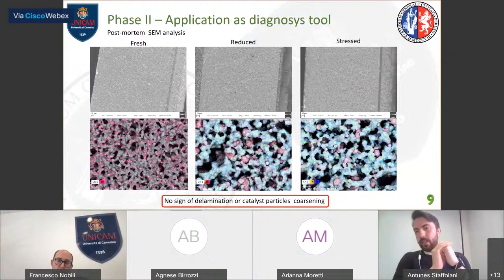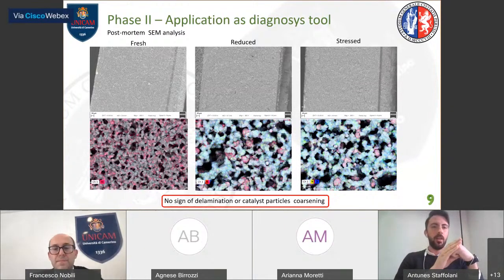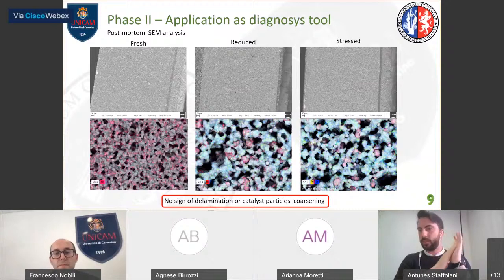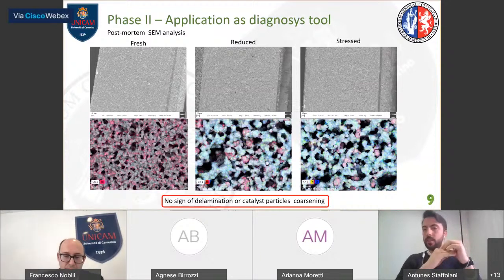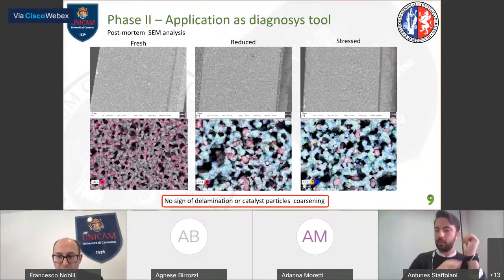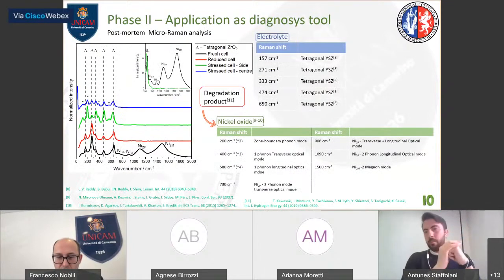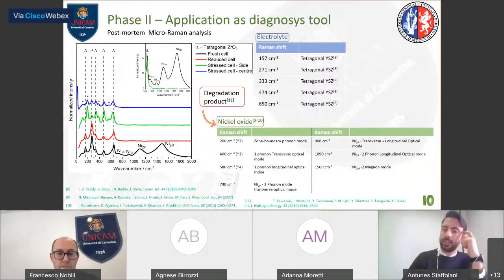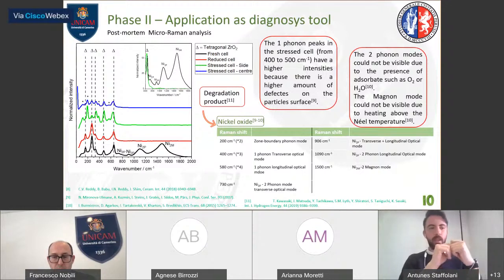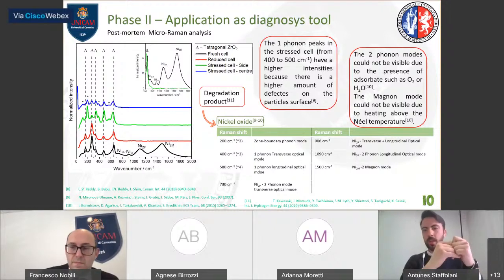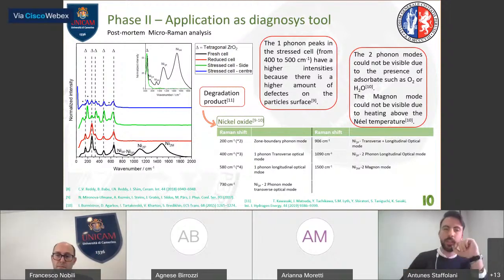So we did the post-mortem SEM analysis, but the cell was pretty well and there wasn't any irreversible damage, no sign of delamination at the electrolyte-electrode interface, nor catalyst particle coarsening. So we also did the micro-Raman analysis, which confirmed that the issues were in the anode. Indeed, on the stressed cell, on both side and center, we observed peaks coming from nickel oxide, which is a quite common degradation product, especially when cells are run at high current density.